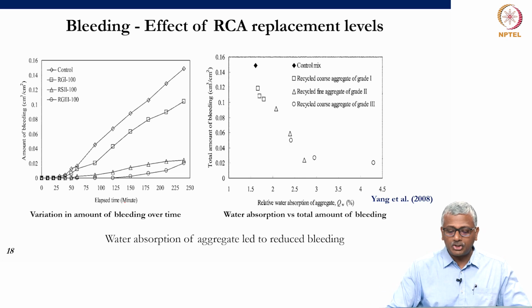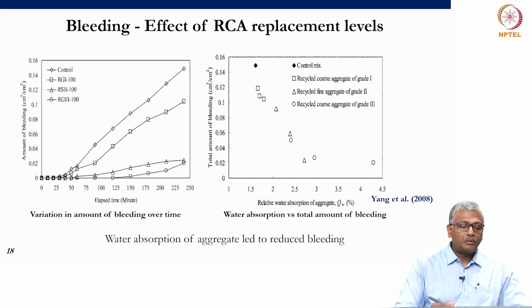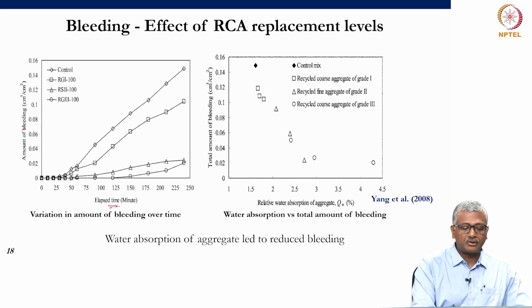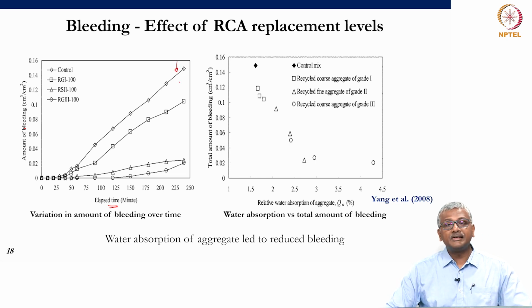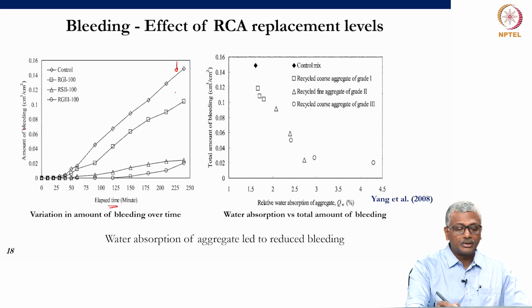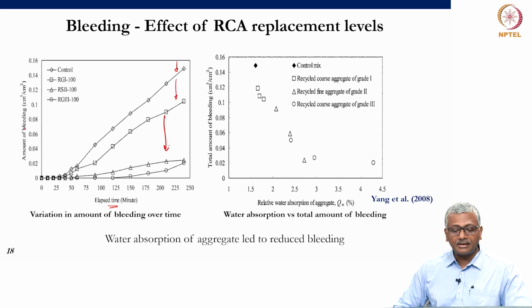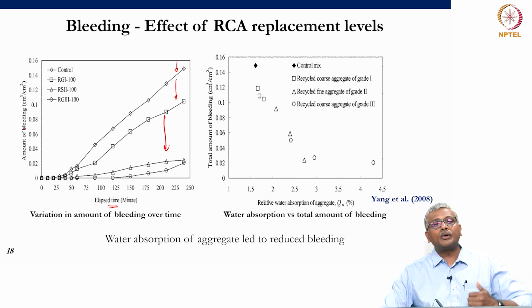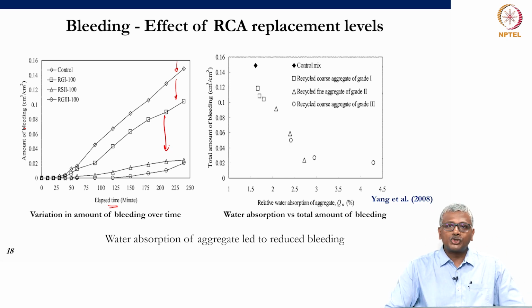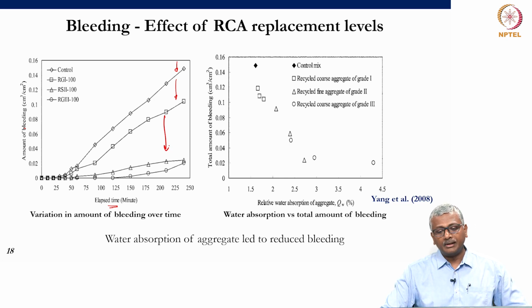Indeed, that is what is being shown by the study by Yang et al., where the amount of bleeding was measured with respect to the elapsed time. For the control concrete, you can see the extent of bleeding is significant. As you use different types or different grades of recycled concrete aggregate, the extent of bleeding seems to come down significantly. So, what this goes to show is the adhered mortar is beneficial with respect to reduction in bleeding.